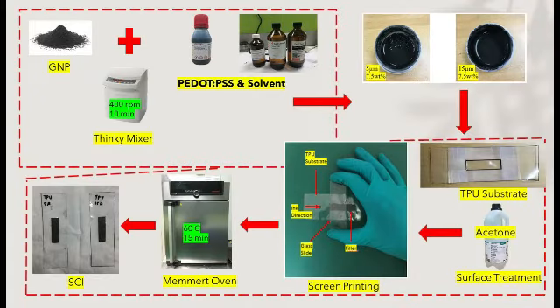All the materials will be mixed together by using a thinky mixer at 400 rpm for 10 minutes. This process is called the mixing process. As the final result from the mixing process, we got final mixtures for the 5 micron and 15 micron. Before we apply the final mixtures on the TPU, prepare the TPU substrate with scotch tape and gently clean any dirt by using acetone. After that, apply the ink on the TPU by the manual screen printing process. Then put it into the oven for the curing process.